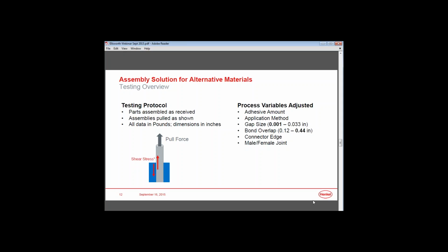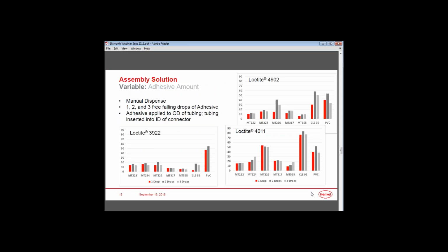The process variables that we wanted to adjust, again, to show the versatility of the adhesive, are the adhesive amount used on the assembly, what application method, the gap size. So we altered the gap size for one test, and I do have in bold the thousandth gap, because if we weren't adjusting the gap, you could be assured the other data is with the thousandth gap, which is similar to a slip fit. The bond overlap, again, we varied that, but you'll see in bold the 0.44 inches is what was used for the majority of the testing, unless we notify. The connector edge style and a male versus female joint. So those are the adjustments that we made. Each of the next slides will address each of those adjustments.